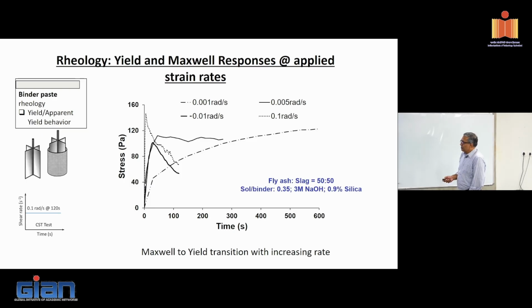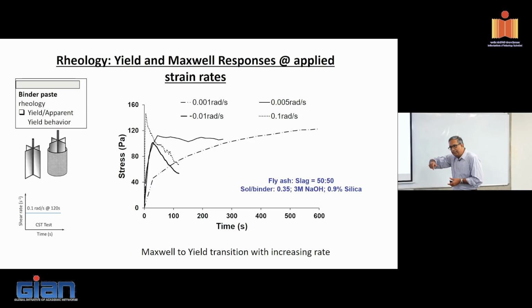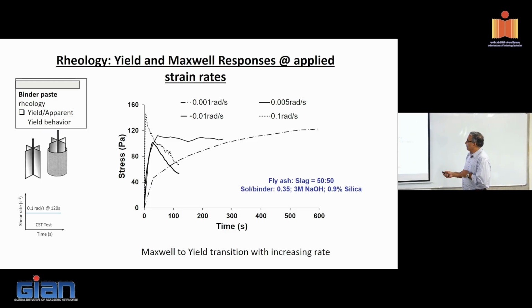Now, I'm doing a constant strain rate experiment. So basically, I'm shearing it. When I shear it fast, look what you get. You get a yield type behavior. Look at this. It basically builds up very quickly to the peak and then it decreases, right? What happens when I slow down the rate? So when I start slowing down the rate, you see what happens? When you go to a very slow rate like 0.001 radians per second, so I'm basically turning the spindle at a very low rate, you see that the resistance slowly builds up.